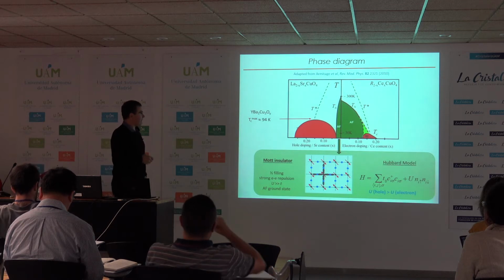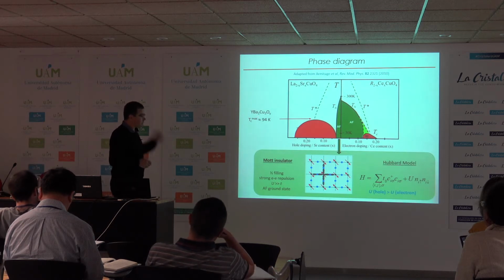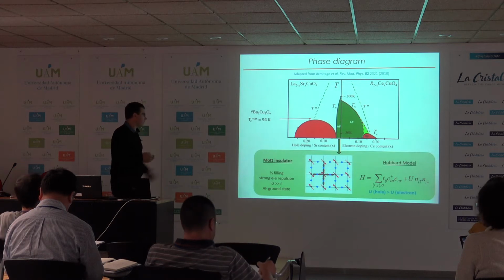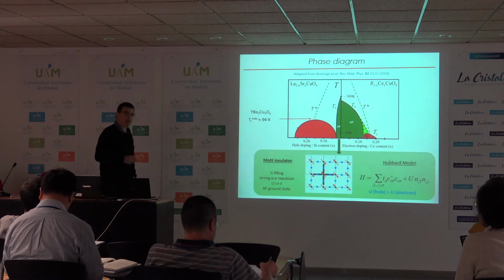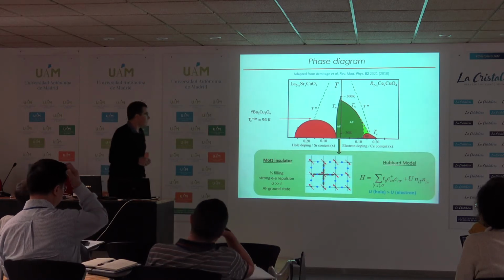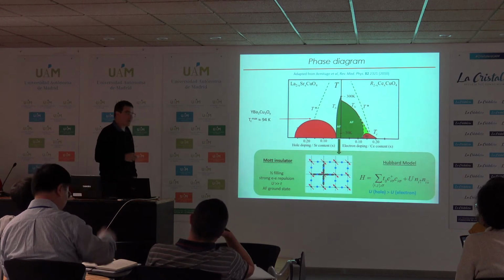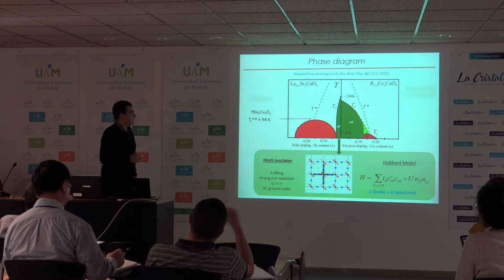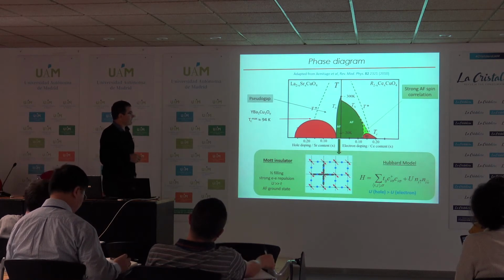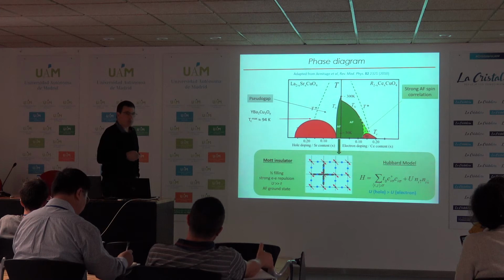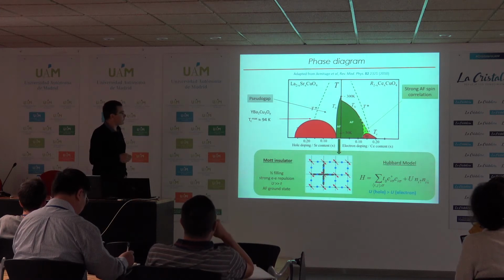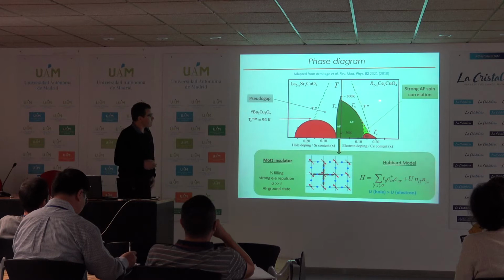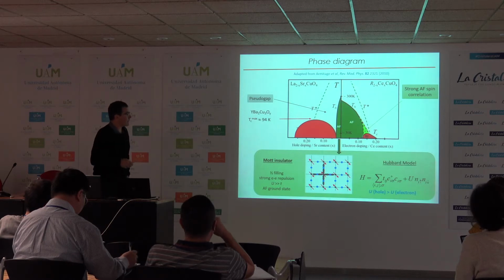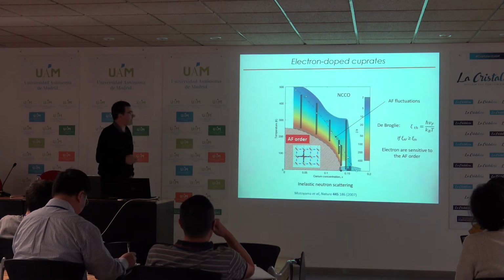The second main difference is not clear on this phase diagram, but when you put the maximum temperature for hole doped cuprate, for instance YBCO, you see that the superconducting transition is much higher for the hole doped cuprate. In fact, it goes up to 133 Kelvin for the three-layer mercury compound. And the other main difference is that there is what we call a pseudogap state, which you have heard about before, for the hole doped cuprate, whereas on the electron doped side you have a strong antiferromagnetic correlation which persists up to a critical doping that I will discuss now.